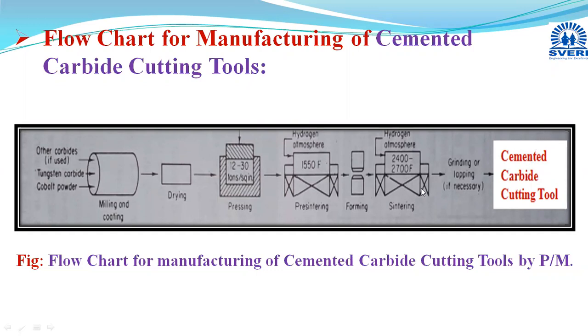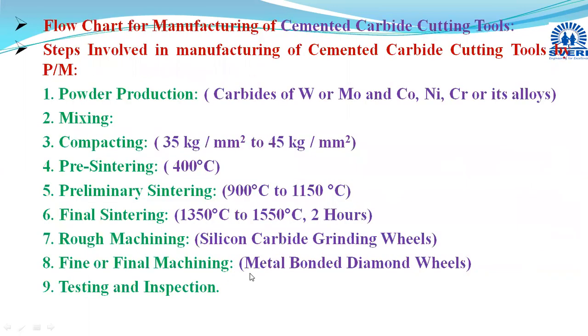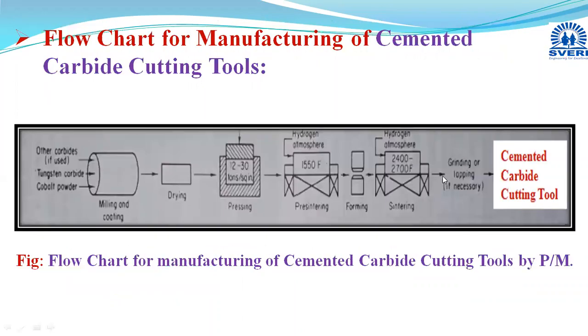Then after sintering, it is subjected to rough and fine, or final, machining. Rough machining is done by silicon carbide grinding wheels, and the final or fine machining is done by metal bonded diamond wheels. Here it is grinding, lapping or machining, and after that the component is manufactured, tested and inspected for different properties. Its shape, size and defects are checked, and if it is found okay, then it is suggested for practical use. So in this way, these cemented carbide cutting tools are manufactured.